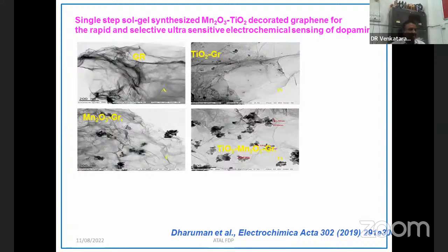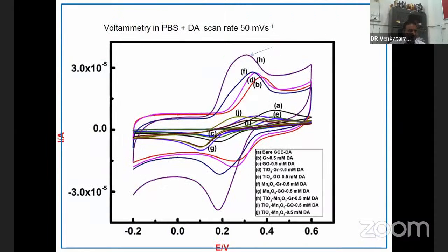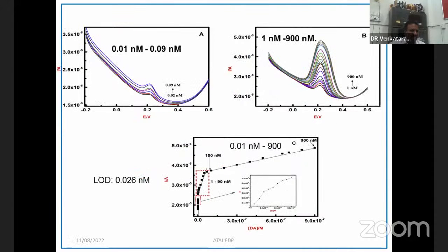And with another method, we also used the binary metal oxides, manganese oxide and titanium oxide. Again, it is modified on a graphene, again used for a dopamine sensor. Here we try to understand how these metal oxides interact with the graphene oxide. Here with 0.5 millimolar dopamine, you can see the composite of titanium oxide and manganese oxide on graphene showed a higher activity for the dopamine sensor.